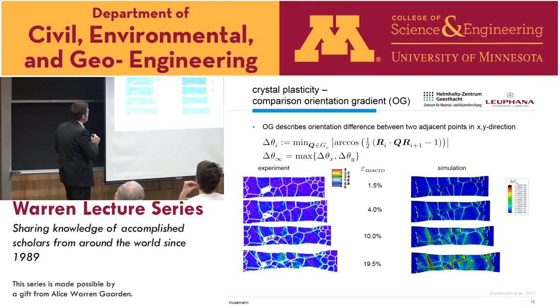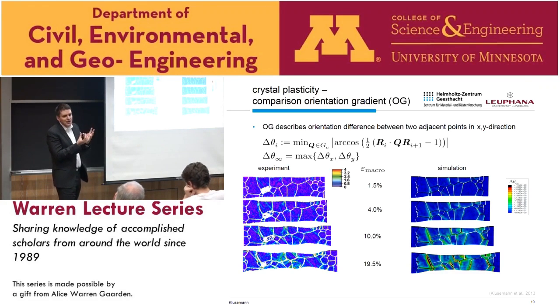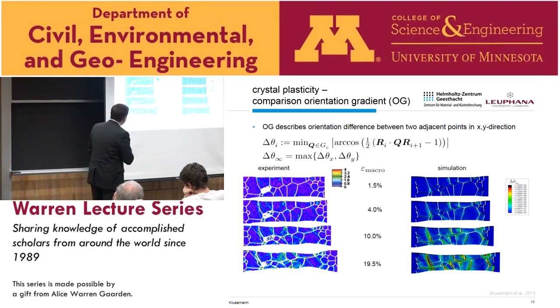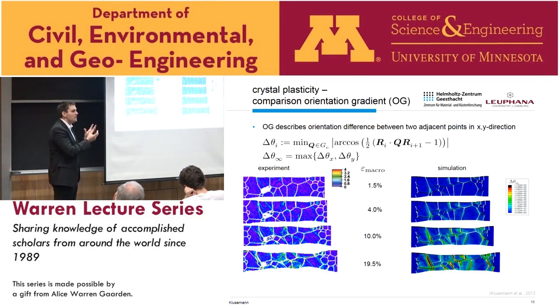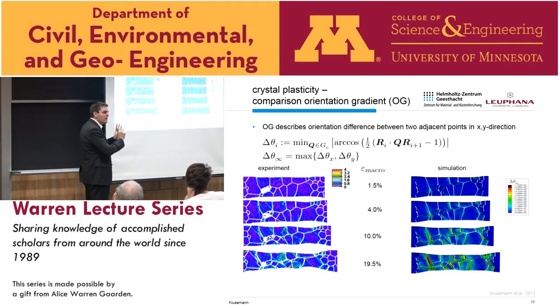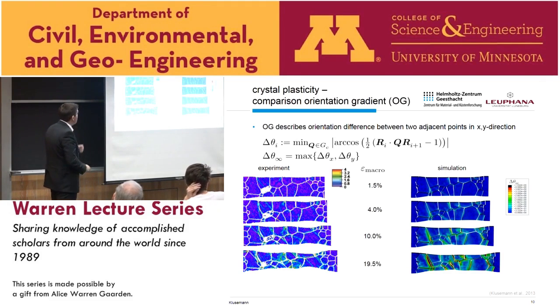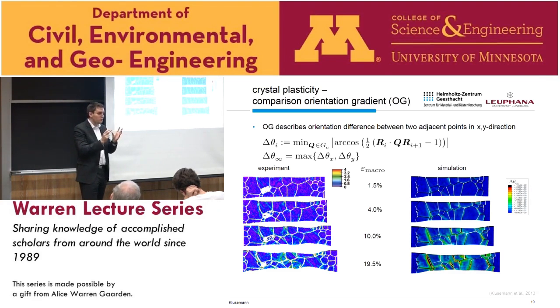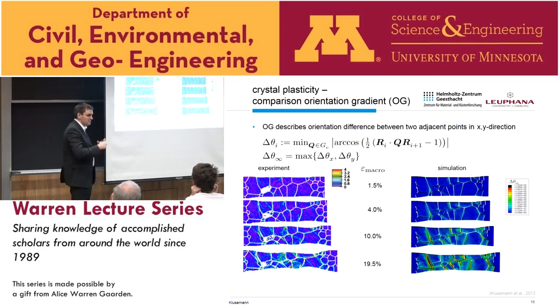So what we did next, we compared the so-called orientation gradient. The orientation gradient is a kind of measurement for the dislocation density, because dislocation density is very hard to measure, as you can imagine. But you can understand the orientation gradient as a kind of local misfit, or local incompatibility, which is similar to something like dislocation density. It's not exactly the same, obviously, but you can at least compare the tendency of where you have the highest development. Orientation gradient is simply calculated based on the misorientation between two neighboring pixels in the experiment, or in the simulation, two neighboring Gauss integration points. So you just take the orientation which you have, and of course you're accounting only for your grain alone, not over the grain boundary, because there you have large misorientations, just inside of the grain.